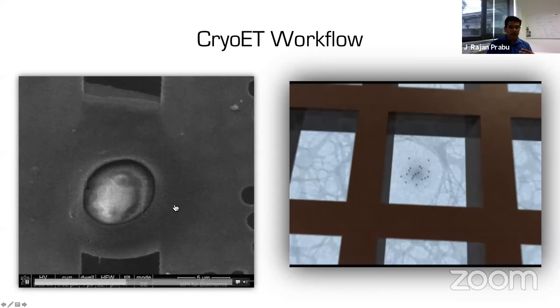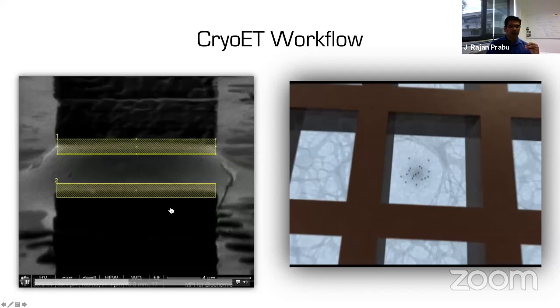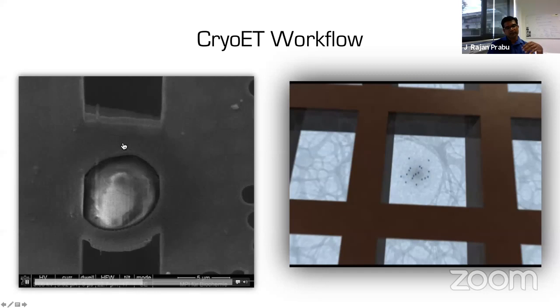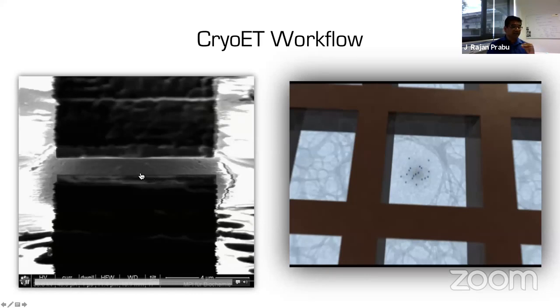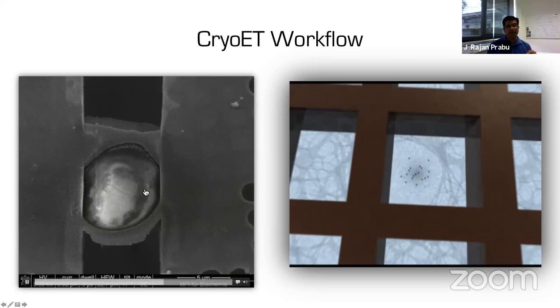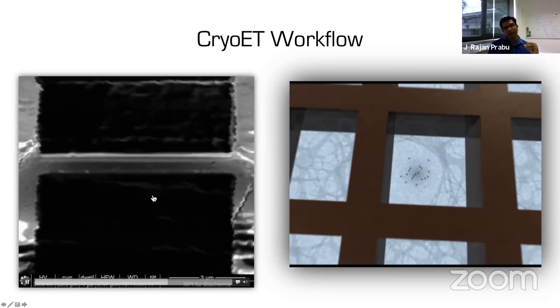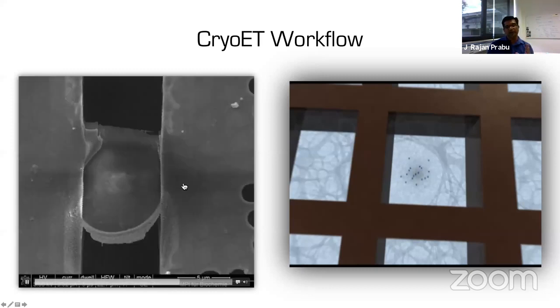And then it's only 200 to 300 nanometers, and you really, really go slow. As you can see, my colleague has done this super slowly. She first moved very roughly, and then goes slowly, one by one, top to bottom. I'm also learning this technique, but it's one of the very difficult things to do. I wouldn't say it's impossible, but getting the skill to form a nicely aligned lamella is not an easy thing to do.